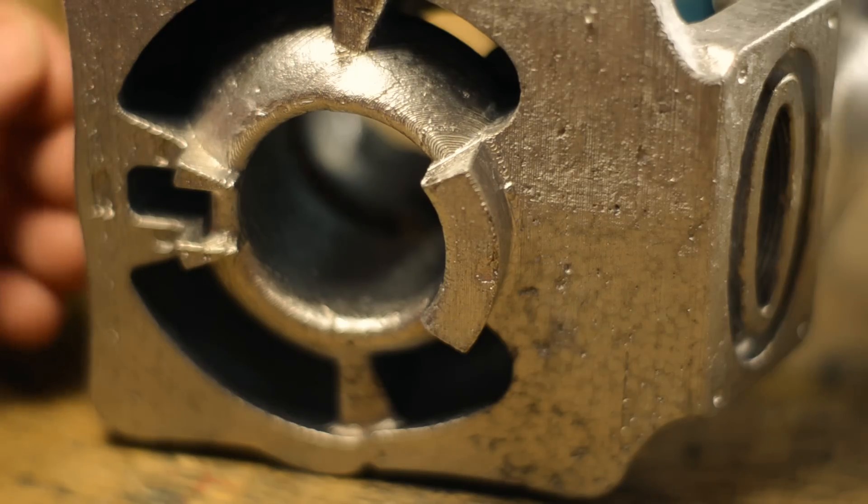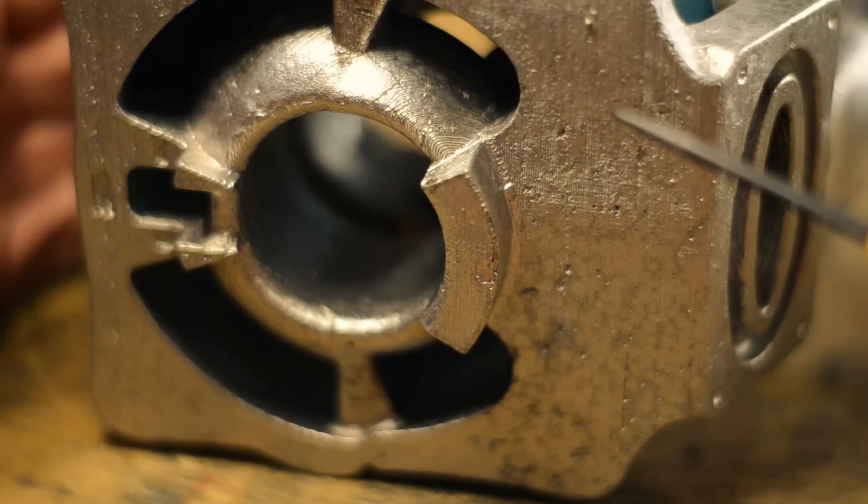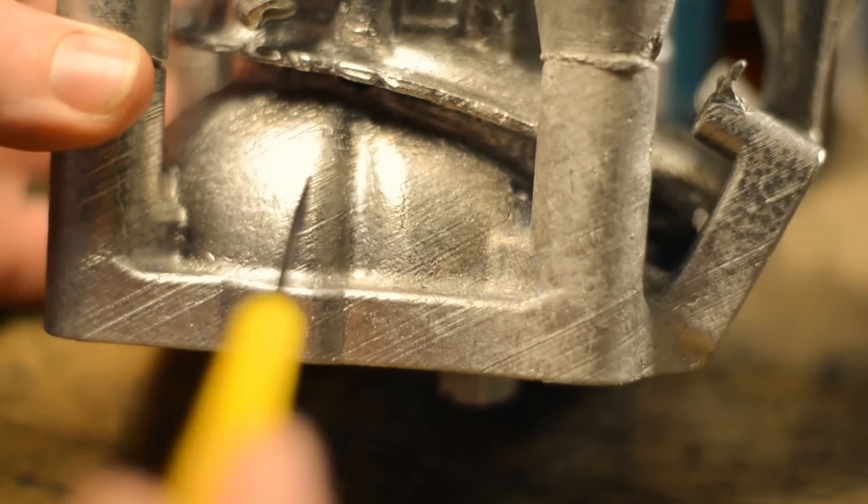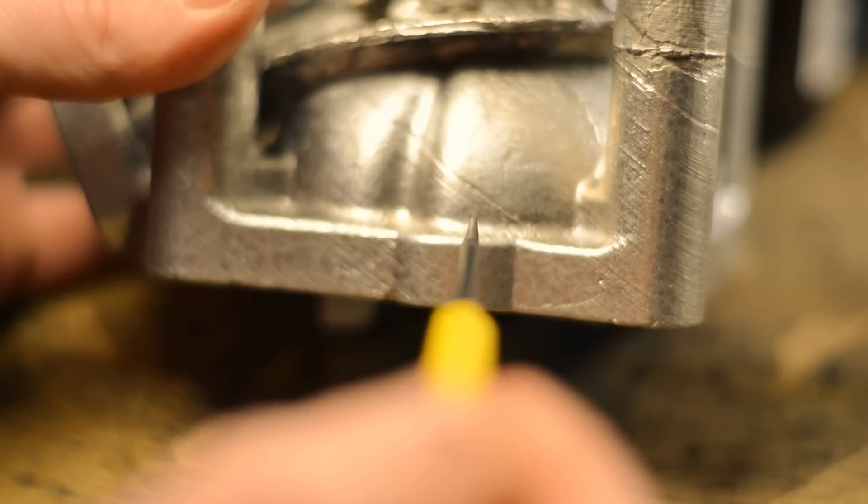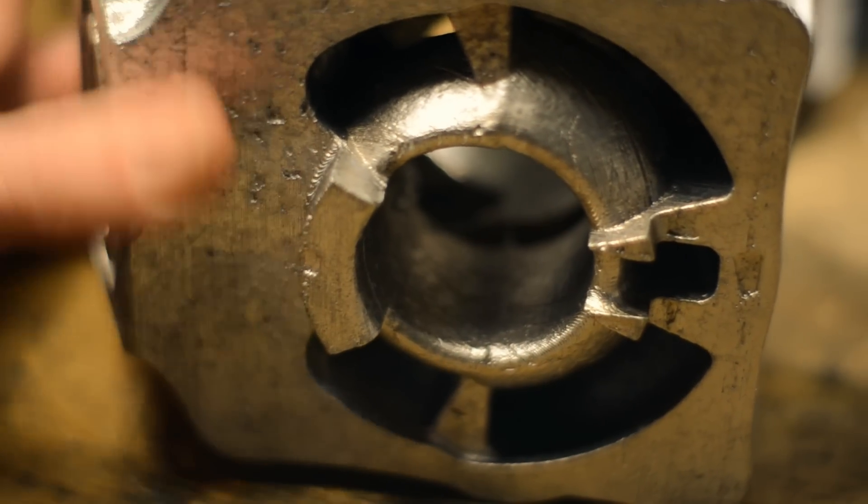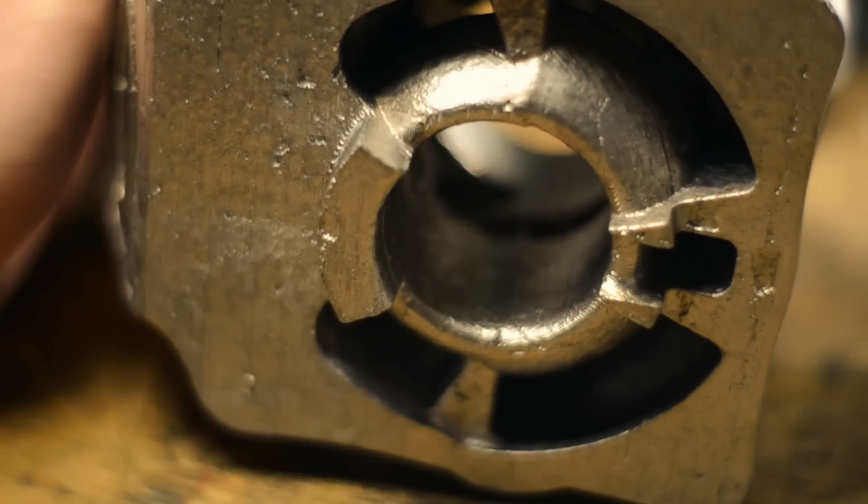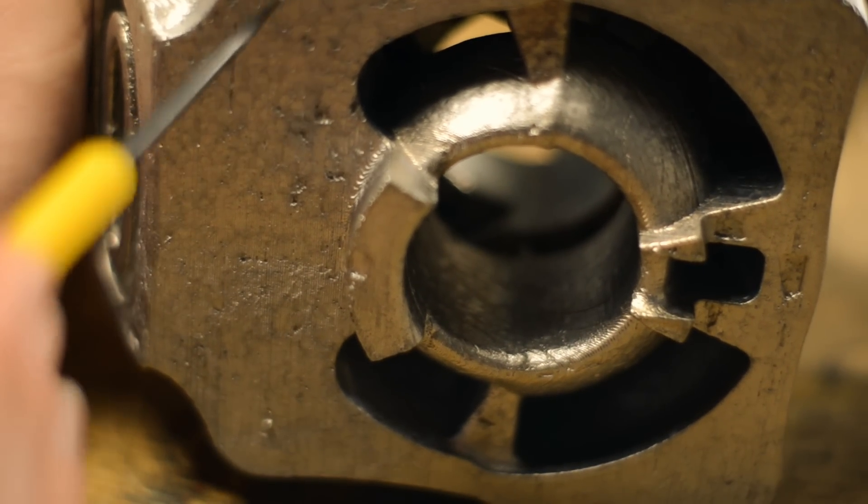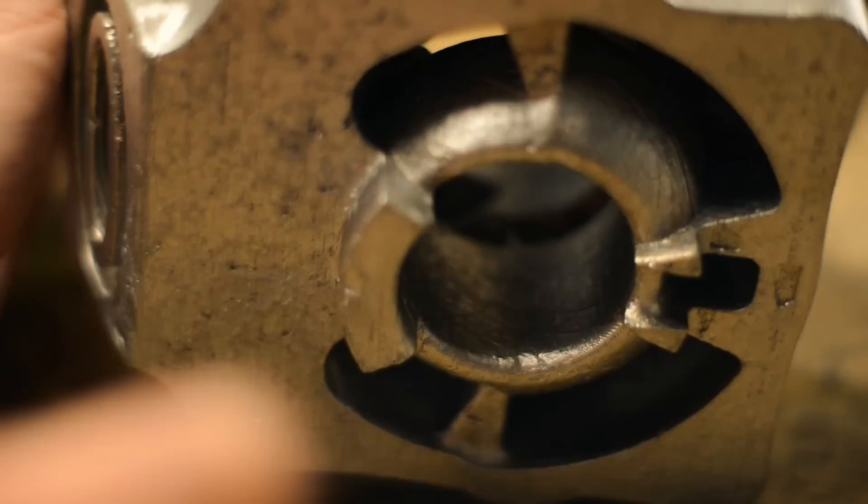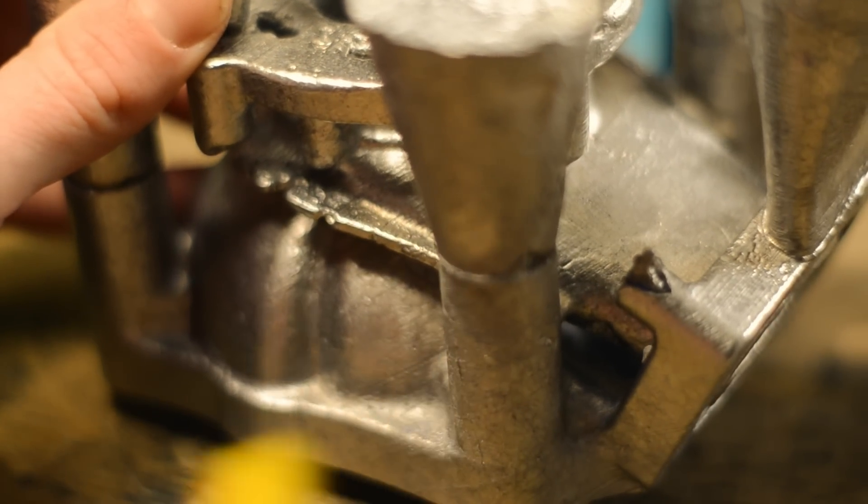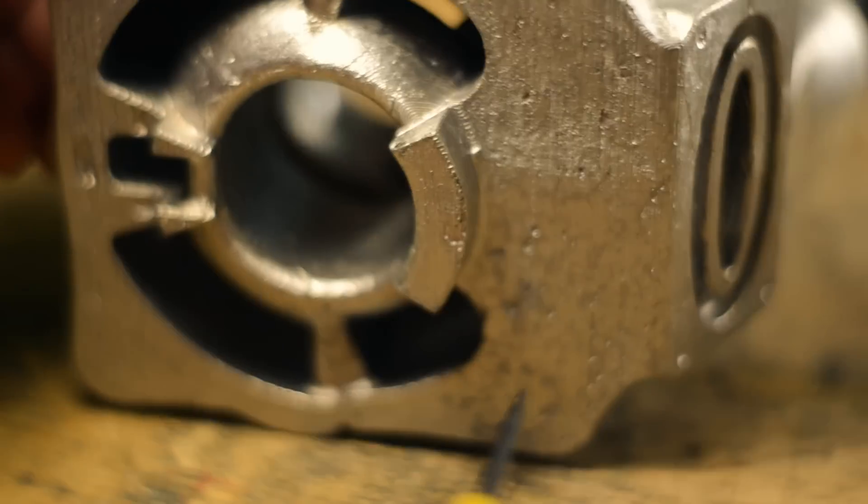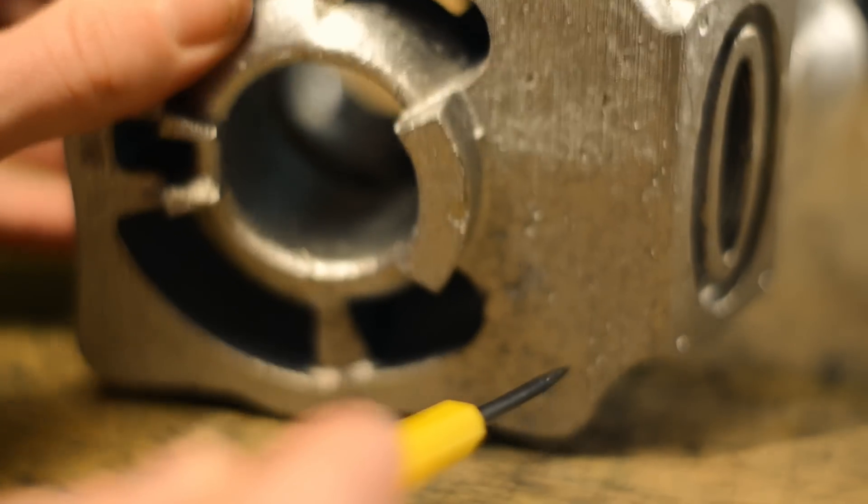Let's start with the bottom here. So actually the bottom half of the whole casting is fairly good. Surface finish is great. You can see all the print lines. There's really no problem with the bottom of the casting except for the porosity you can see here, and I think that's caused by the initial slug of impurities going down with the aluminum and ending up here in the bottom corner.